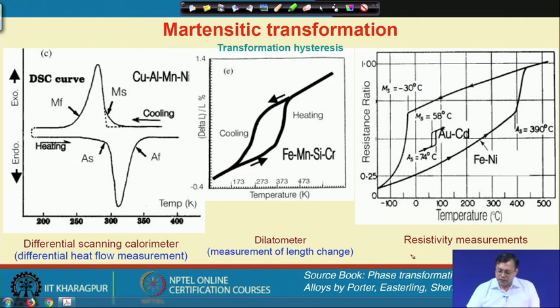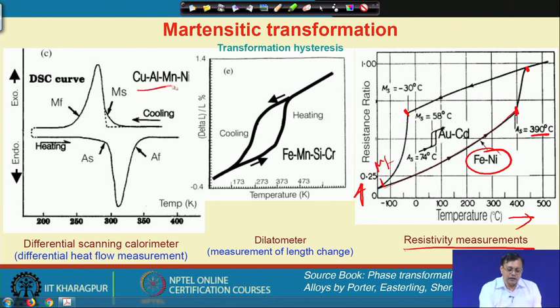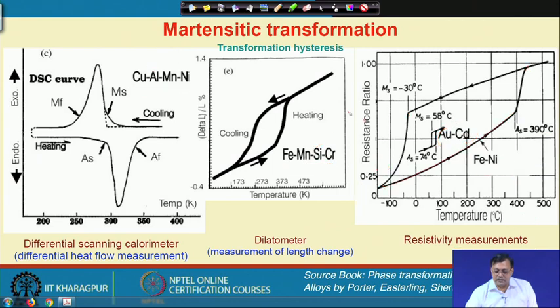In the case of resistivity measurement, a very similar thing has been observed, the similar hysteresis we are talking about. In this particular case, we have the temperature and the resistance axis, in an iron nickel system. The transformation begins here, which is the austenite start, here is the austenite finish, here is the martensite start and here is the martensite finish. So, you can see there are several systems: copper, aluminum, manganese, nickel, here also with chromium, here the iron nickel system and the gold cadmium system. So, martensitic transformation occurs in many different systems, and all those systems show some hysteresis, where the hysteresis could be small or larger.